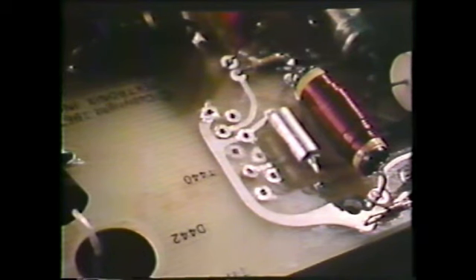Excess heat ruins boards. Try not to heat a connection longer than 2 seconds. If more than 2 seconds is required, your tip may not be properly tinned, or your iron wattage is too low. Allow connections to thoroughly cool before reapplying heat. Some specific board materials may not even tolerate 2 seconds of heating.